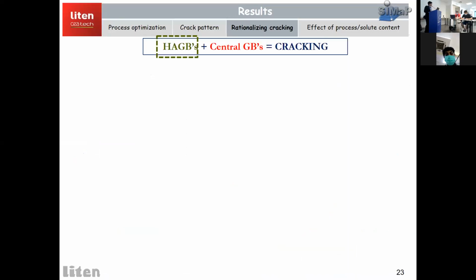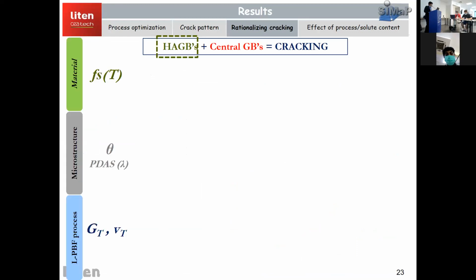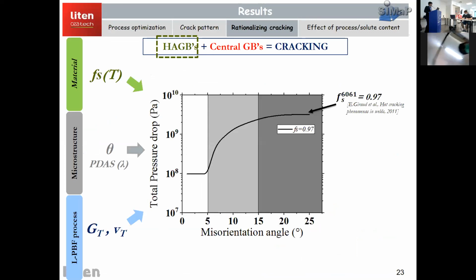Now, to finally address why high angle grain boundaries were cracking: based on our different inputs, the material, the microstructure, and the L-PBF process parameters, we were finally able to estimate the pressure drop as a function of misorientation angle. Again, we chose the same solid fraction value of 0.97 for the sake of simplicity. For the total pressure drop, we see clearly that after a misorientation of 5 degrees, there is a jump in the pressure drop.